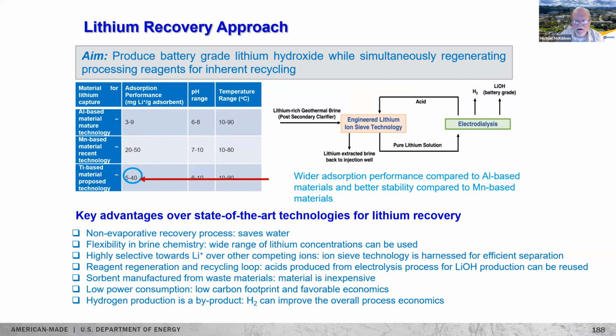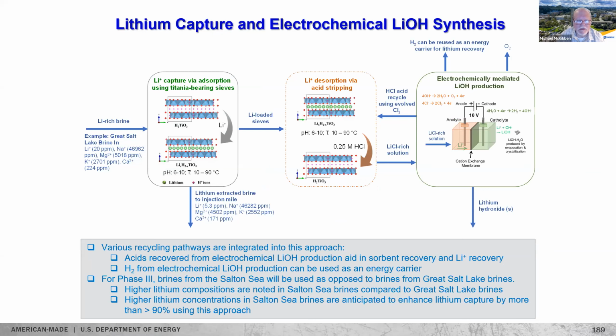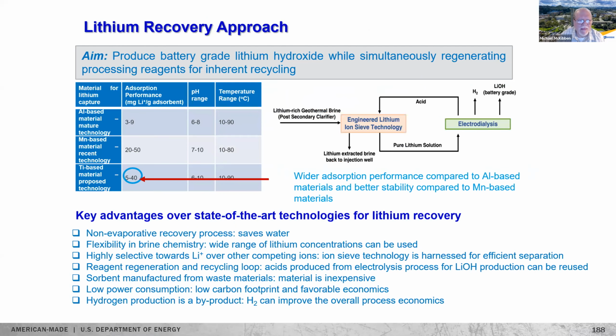Technologies already exist for removing silica from geothermal brines. For example, mesoscale fluidic separators have already been developed and tested with geothermal brines and patented by PNNL for silica separation. The current operators at the Salton Sea field also use patented post-flash reactor clarifier technology to reduce silica and iron precipitation in brines prior to attempting lithium recovery. So minimizing further brine cooling during lithium extraction is critical. Please back up the slide. Our technology addresses the challenge of developing stable materials for lithium separation at plant temperatures and inherent recycling of reagents and water for efficient lithium recovery.